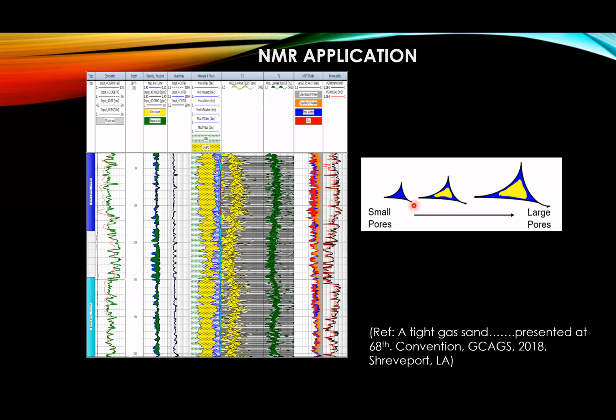Now here I'm just showing you some pore size variations. So here, this is an extremely small pore. This is one grain here, another grain here, another grain here. So this is a pore, and it's filled with such a small pore that it's all bound water. So the blue indicates bound water. As the pore size increases slightly, you can see that you start to have some free fluid coming in. So here now, you see some free fluid, but you still have some bound fluid that is not flowing. And when you have a larger pore, you are seeing a considerable amount of free fluid, but there's still a significant amount of bound fluid there.